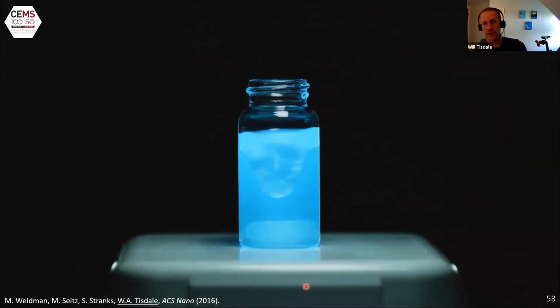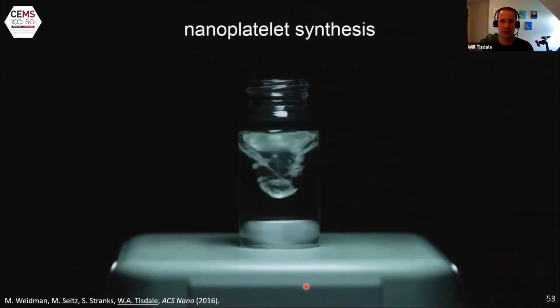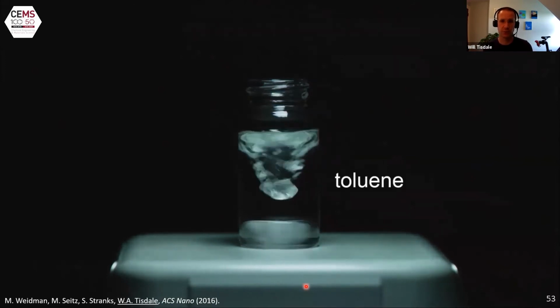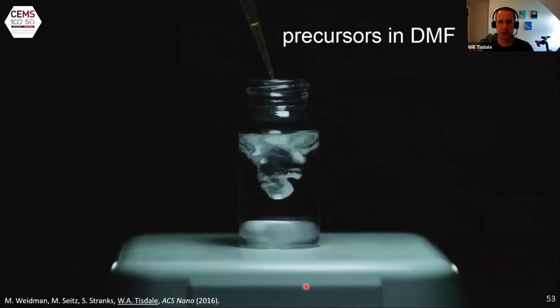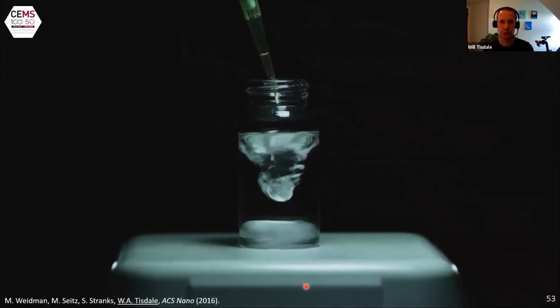You can control the average thickness of the material you get by controlling effectively the surface area to volume ratio, by controlling the ratio of the surfactant to the bulk-like precursors that you have in your initial formulation.